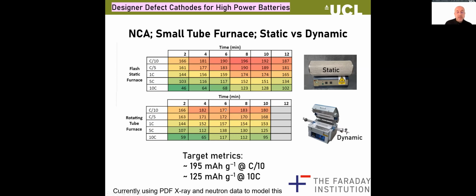Here are some early results at a specific temperature, because I haven't mentioned the temperature here. What we can see is that in the first experiments we're doing on that, we're getting ballpark in the same region. And remember, the powder is in direct contact with the tube here, whereas it's not directly in contact with the tube there. So that's why there's a difference between the values at 10C, but we are ballpark getting near to our target. So I'm very excited about that, and I think between now and January there's a big job to be done there.